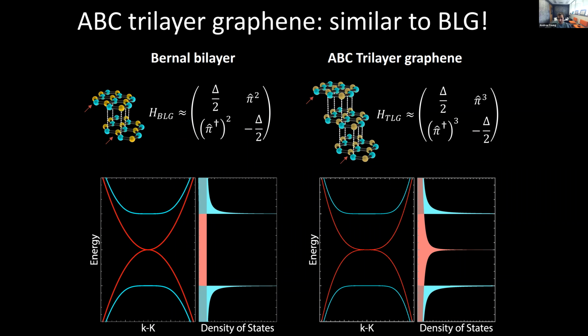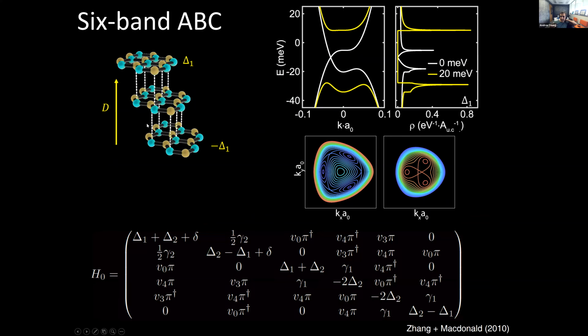And those have very different electronic structures, but in particular, ABC trilayer, and indeed rhombohedral graphites, all basically resemble Bernal bilayer graphene in the schematic picture of their band structure. And you can see that from these low energy Hamiltonians, where the only thing that's changed is actually just the power to which this px plus i py or px minus i py operator is raised on the off-diagonal term. So their band structures actually look very similar. The only difference is that this Van Hove singularity, the divergence of the density of states, is increased somewhat in ABC trilayer.